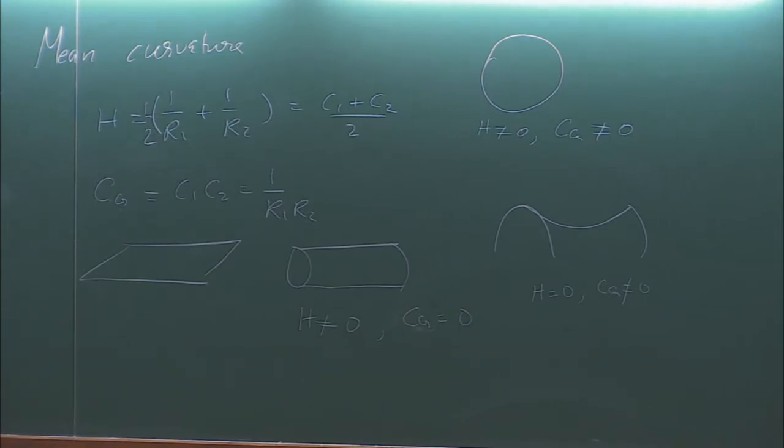Okay. So now I can write down this free energy expression. Can there be a coupling between the stretching and the bending, in the sense that there is a quadratic term which is related to A minus A zero times C? No. In this, we are only considering the cases where the membrane is thin enough that there is no coupling between the bending and the stretching. These are two independent deformations.